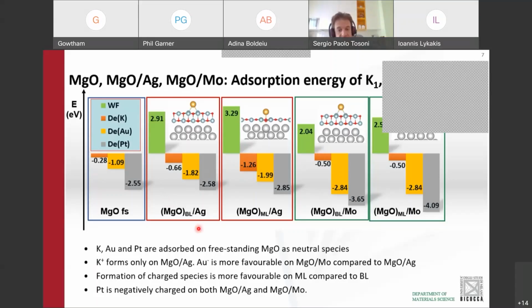Platinum is negatively charged on both silver and molybdenum supported MgO, but as you can see, it does not display a very clear trend with respect to the work function, and its binding energy is very strong also on freestanding MgO.